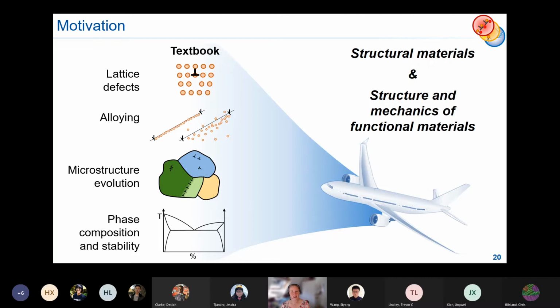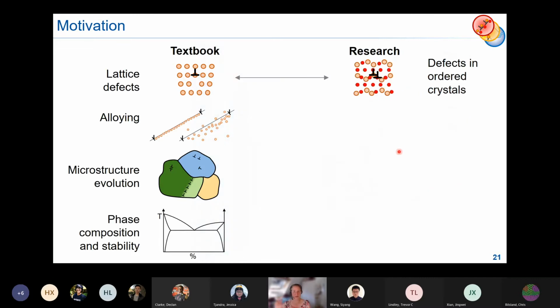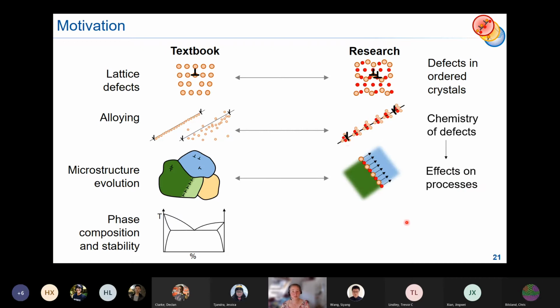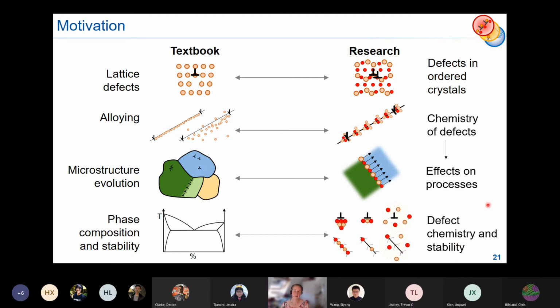That's what we do in textbooks and in teaching, and actually in research we go a lot further, and there are a lot of sites that we work on. I've already told you that in ordered crystals, even just knowing which defects we have might be a difficulty. We also know, though, that when these defects are alloyed, they are not just some continuous thing like a Cottrell cloud. Actually, you get chemistry and structure interacting very strongly at the defects. We call this a defect phase, as you see. You might have heard the word complexion as well, a distinct structure that forms at a defect and not anywhere else. And of course, these will affect microstructural processes like grain boundary mobility. So then you have an effect on microstructure evolution or on plasticity. And the main point that we wanted to look at is that we should be able to do that for the defects just the same way as we do that for crystalline phases.